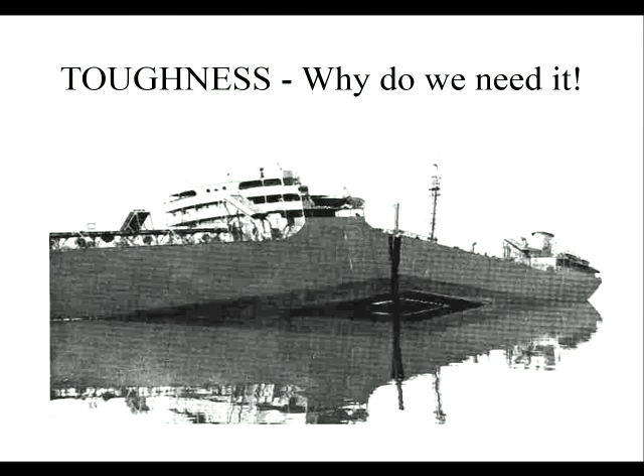You can imagine a wave at each end supporting the boat and then nothing in the middle, and the whole weight of the boat then acts downwards. There's a bending stress, maximum tensile stress at the bottom, a defect, and a crack runs up. So the toughness hadn't been taken into consideration, the strength had. So this was the right thickness of steel, the right loading conditions, but it couldn't cope with the defects that were present, and the toughness of the steel was not good enough. So we developed ways to look at how to improve steel toughness over the past 50 years or so. And Dr. Euler will say a little bit more about that in the next lecture. So that's where I'll stop.